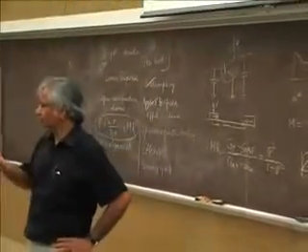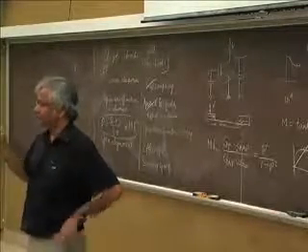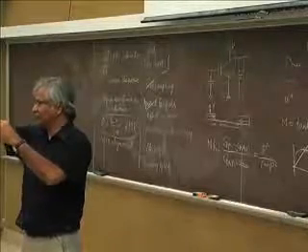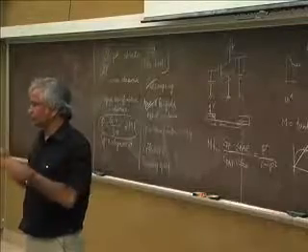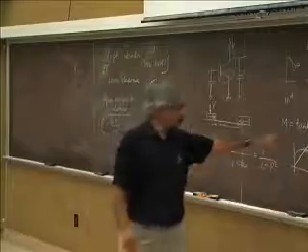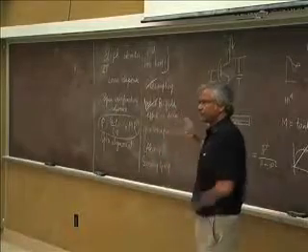Now, in any of these descriptions in ordinary semiconductors, no one seems to worry about it, because in any case, the spin densities involved are like 1 in a million, which means if you have 1 at a particular atom, the next one is like after a million atoms or so. Relatively rare, not very dense really. In magnets, you worry about such things. And so in the equations people use to describe magnets, the LLG equation, there is, of course, an internal field, etc.